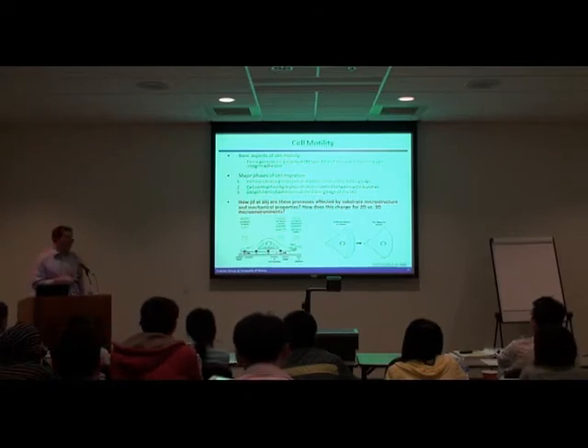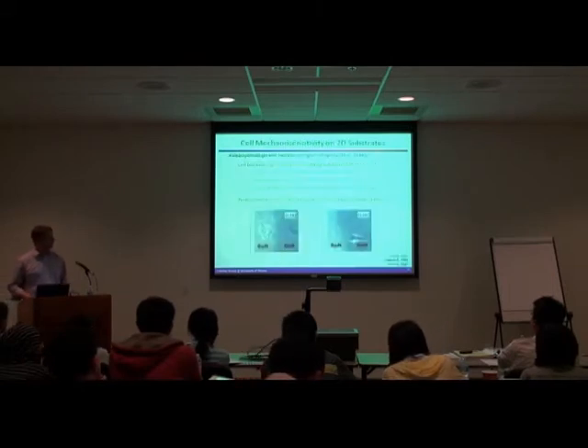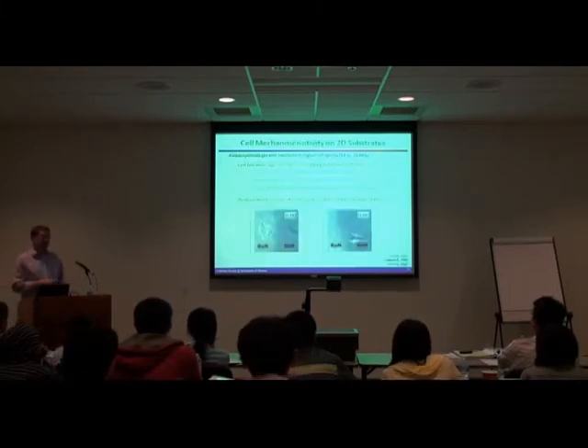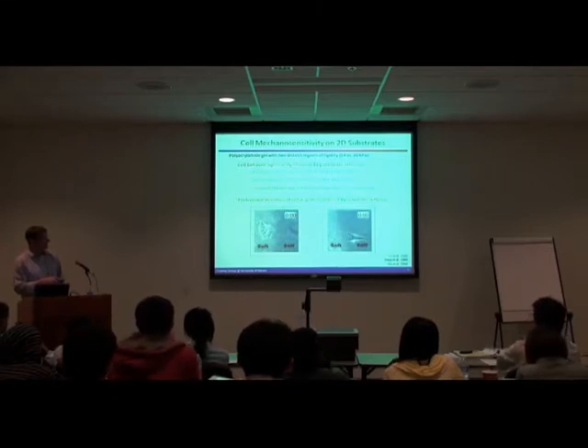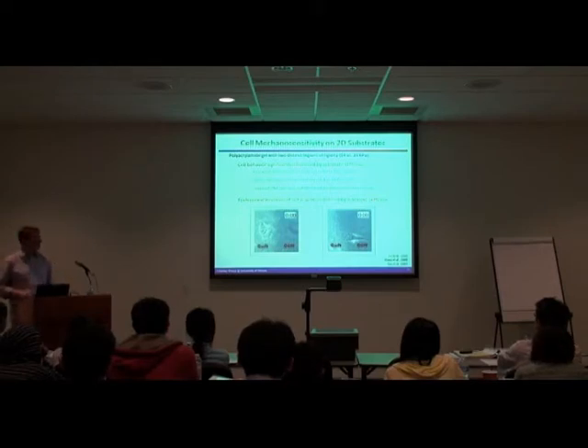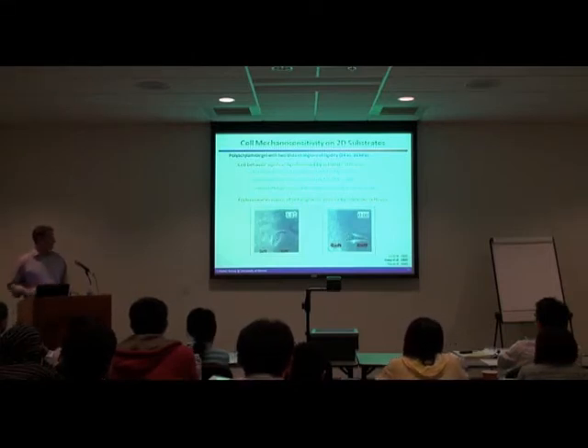The 2D environment is one in which a number of groups have looked at cell motility several times. One of the classic examples is Yu-Li Wang's group, who was at UMass when we did this with Carnegie Mellon. They were using polyacrylamide systems with tuned mechanical properties to look at fibroblast migration. Not only did the underlying mechanical properties of the membrane affect a number of other features such as traction forces, DNA synthesis, and apoptosis, it also affected cell migration. They could watch cells on an interface between a soft and a stiff biomaterial, where the difference was only about 14 to 20 kilopascals, which is not something you and I can really feel. But you could see quite substantially that cells would move quite happily from the soft onto the stiff side of the membrane.